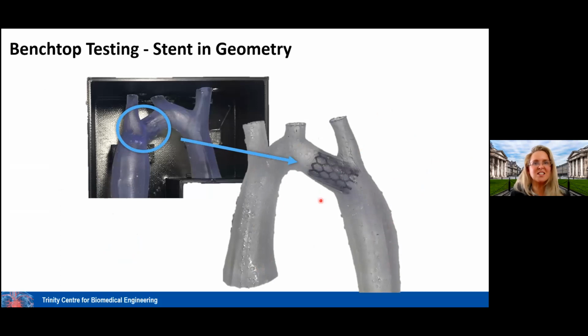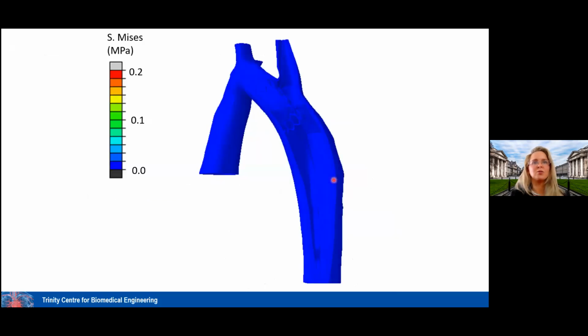And then because we've printed the stent itself, we can implant that stent on a benchtop. So in a benchtop model, we can, in a way, pre-clinically ascertain, does that stent suit this coarctation? Is it going to open up the vessel in the appropriate way? And therefore, is it suitable for this application? So that's a real bonus, because you can physically hold this. Surgeons can look at it, they can plan their surgery and see where they should best place that stent. But then in the virtual model, we also can now look at that stent implantation. So this is just one of the stents, the honeycomb structure, being placed virtually inside that real vessel geometry of that 5-year-old with coarctation, and looking at how that stent will open up that vessel.